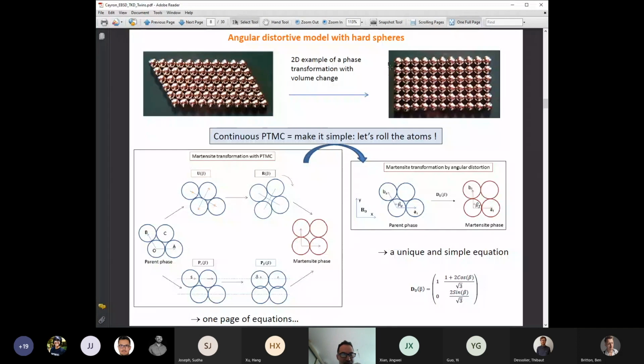So if you look at the left image, it's a stacking of balls with a hexagonal order. And if you look at the right, you see a square lattice form, and how you go from the left to the right. This is a phase transformation. How can you make this transformation? If you look at what PTMC says, for this square martensitic transformation they imagine two ways, one with a stretch and a rotation, and another way that is a shear with a dilatation. And the theory tells you that both paths lead to the same final structure and same final orientation.